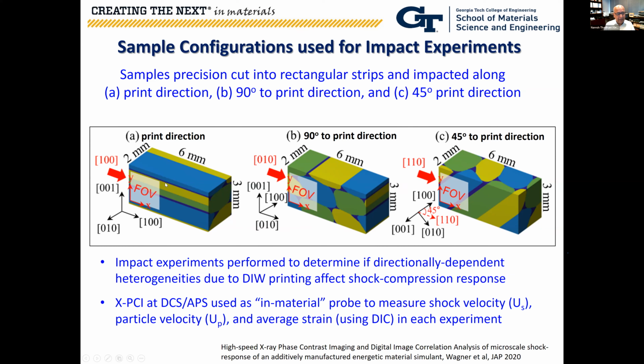Upon impact, the shock wave travels this 6 millimeter length of the material. The X-ray field of view is about 2 millimeters by 2 millimeters, so even though the shock travels a longer distance, this is the region we view. The X-ray probes a 2 millimeter thickness of the sample. That's how the setup was.